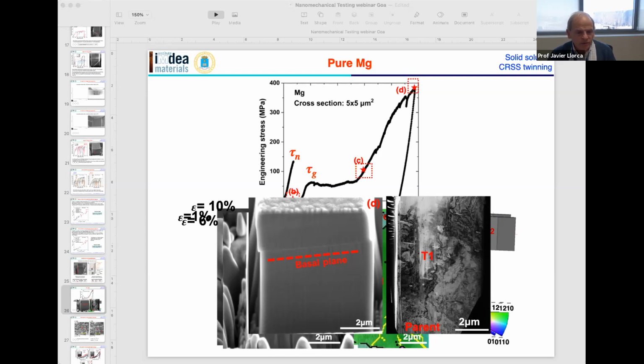And finally, as I told you, when you have deformed the pillar up to 10%, this is a TEM image. And basically, in this particular orientation, where you have the zone axis [2-1-10] and the g vector is 0002, in this region here, you have the visibility condition. So you can see this location with c components. This is for the twin material. This is in the parent. In the parent, you don't have c component dislocations.